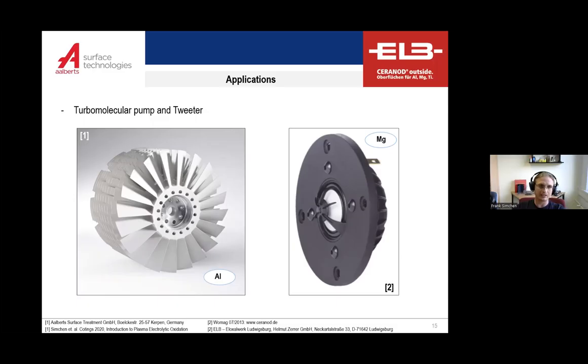And if you transport corrosive etching gases, like in the chip industry or in the semiconductor industry, hydrofluoric gas, then that's also a big challenge for the corrosion protection. And with PEO coatings, you can fulfill this request. So the substrate is not heavy because it's made from aluminum. The coating is not heavy because it's made from aluminum oxide. The coating offers a good resistance against the corrosive stresses. And we have to deal here with an unbelievably complicated substrate geometry. There are other methods for applying oxide ceramic coatings, for example, thermal spraying, but it would not be easy to apply any thermal spray coating on this component. But with PEO, you really can deal with this complicated component geometry. So you can go behind all these undercuts.